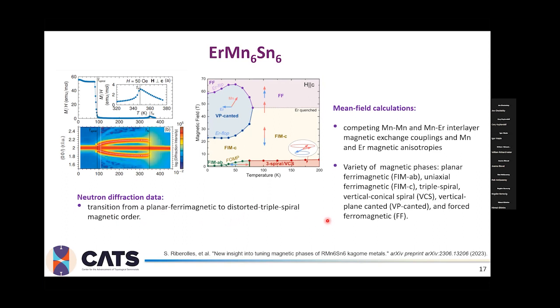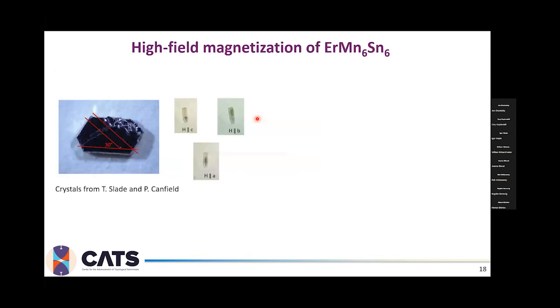And again, with the theoretical calculation, we were able to find out that the magnetic field diagram along the C direction looks very interesting and forms some bubble with this vertical plane canted phase enclosed. So we figured that might be a great example to study and investigate in detail all the magnetic phases in this compound, and also check if it has any influence on the topological properties.